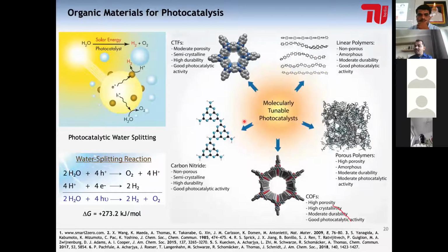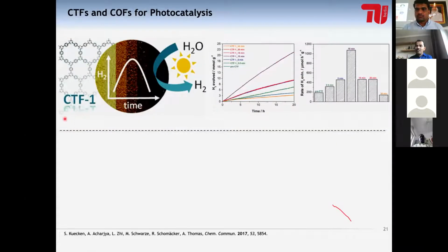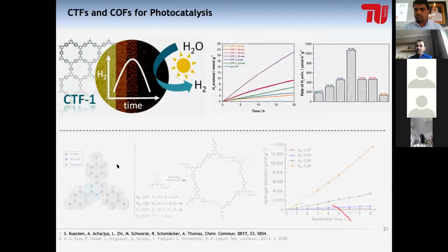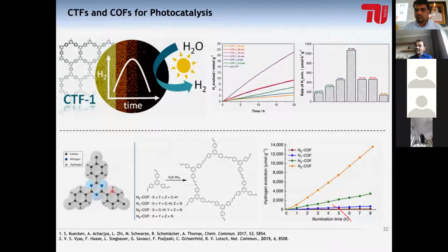So where exactly is this field going? In carbon nitride, in 2009 in our group, we first showed that carbon nitride, a completely organic, semi-crystalline material, can do photocatalysis and can catalyze water splitting very, very efficiently. There are covalent triazine frameworks, different linear polymers and porous polymers which can do this job. But what is happening with covalent organic frameworks? Are these materials usable for this application? Till the point we were working, there were just a couple of reports showing that covalent triazine frameworks made from triazine moieties, as well as covalent organic frameworks with triazine in their backbone, can be used for photocatalytic water splitting. But this field was not going anywhere beyond that.